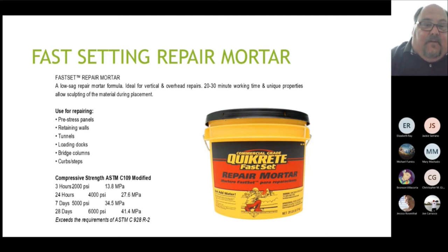The nice thing about this one is just like the vinyl concrete patch, you do not need any other bonding agent with it. No fortifier, no bonding adhesive. These have that in the mix. So what that means is that's one less step, one less thing for you to mix. The same applies with this as far as surface prep. You just make sure it's clean, damp, free of loose debris.